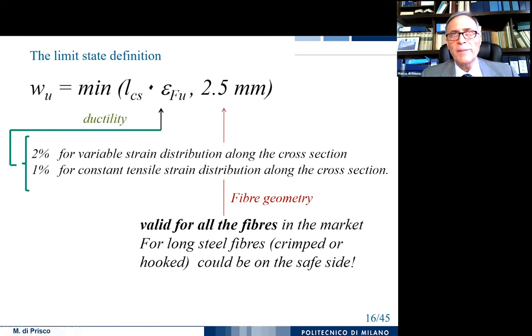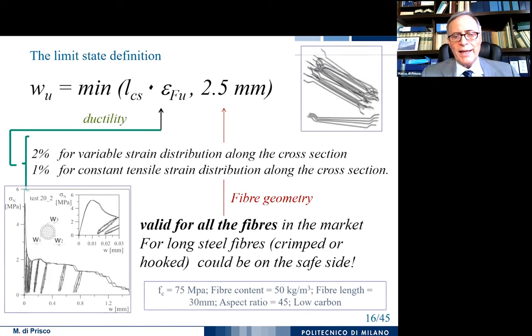Then there is also a problem related to fiber geometry. So we know that if we exceed 2.5 millimeter of crack mouth opening displacement, we could have a lot of problems for a lot of types of fibers that are sold at the moment in the market. And that means that it's better to close at that value in order to be always on the safe side. Well, it's important to know that even if we accept the 2.5 millimeter as a final crack opening, for many cases, for fibers characterized by a length which is even around 30 millimeter, you could have a value which is very close to zero for a crack opening which is much smaller than 2.5 millimeter.